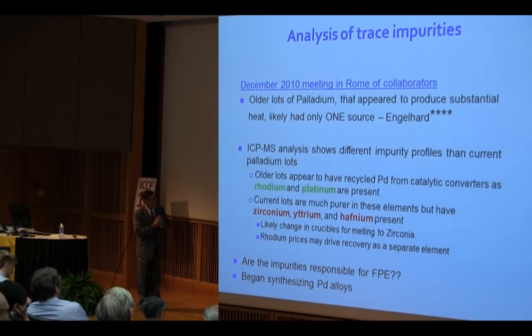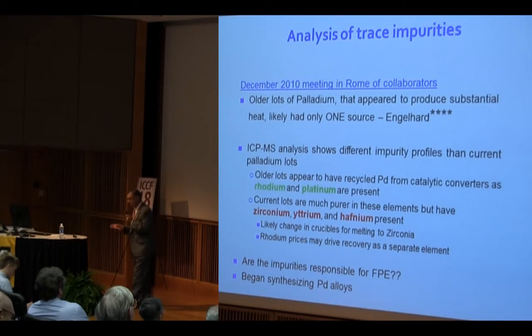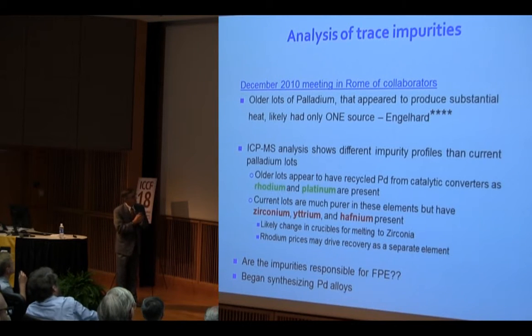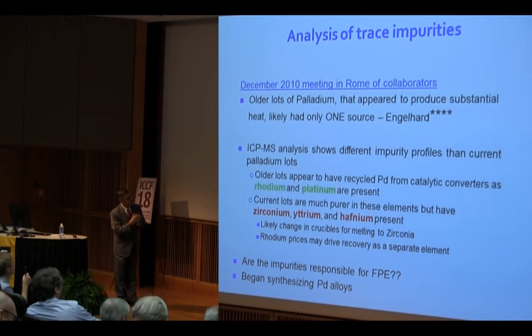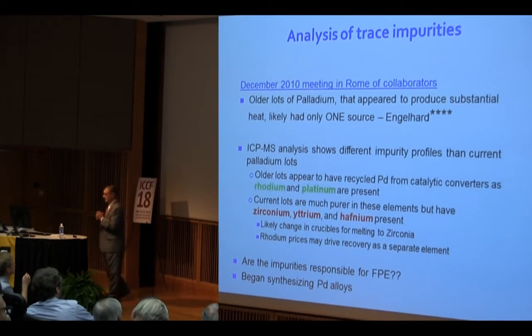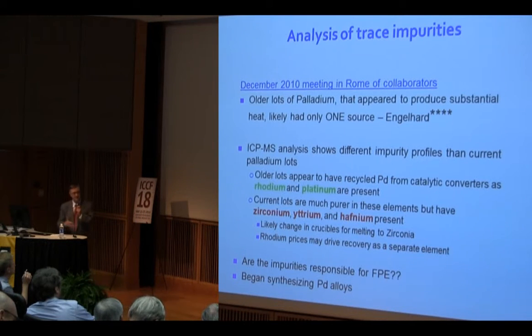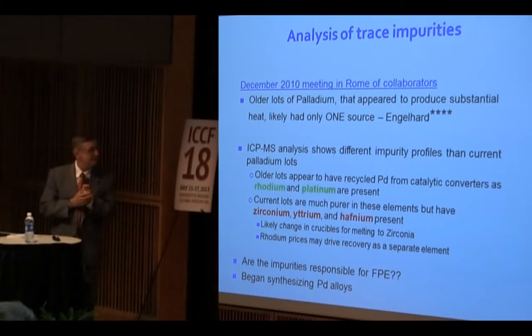And likely the change was due to switching from aluminum to zirconium boats to do this. It's speculated that for prices, they then wanted to get that palladium and rhodium out of the material and resell it, so that's why they changed the process. So one of the goals, which we are going to do at SKINR actually, is start making more alloys, trying to get back to this kind of impurity makeup in the material. So anyway, that's a rationalization for what might be occurring and why this morphology is so difficult to get in the material. So that was one comment.